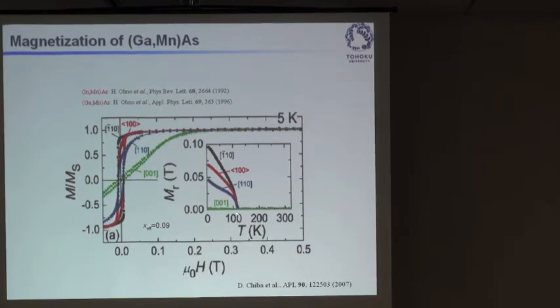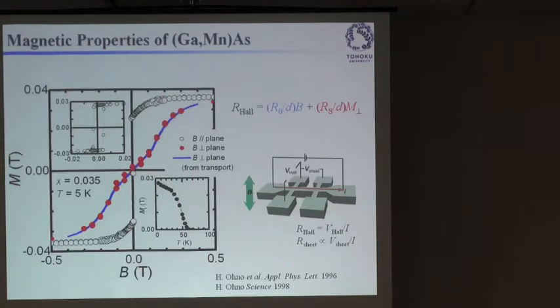Okay, and from the temperature dependence of this remanent magnetization, we see that our transition temperature is somewhere around 110 Kelvin in this case. The highest transition temperature so far is about 190. I will come back to this later. We also noticed that we have a built-in magnetometer, so we do not need to measure our magnetization by using, for example, a SQUID magnetometer.